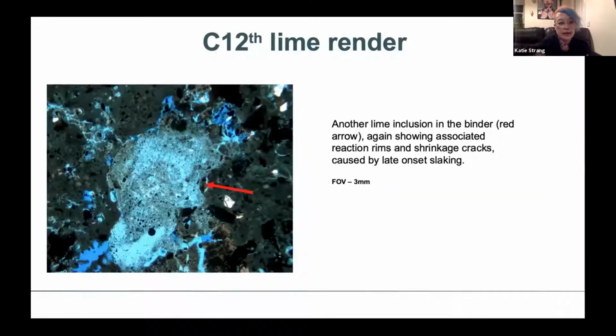So having a look at another lime inclusion in here, this again shows quite a lot of cracking around the edge. And there are these spaces with really blue areas of porosity, which means these are completely isolated and being filled up with that blue resin. And again, because you've got this cracking around the outside, normally you can't see it very well in this image, you get some compression around the edges with the paste or the binder. And that just tells you that it was probably late onset slaking. So this happened while that particle was in the material.